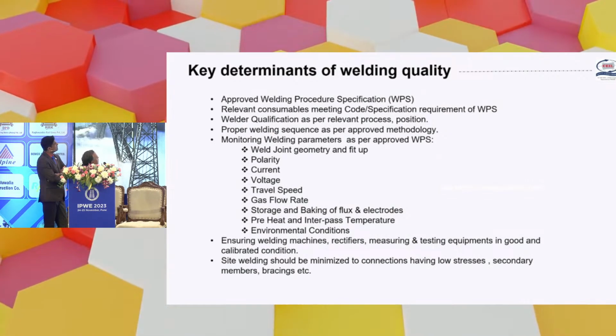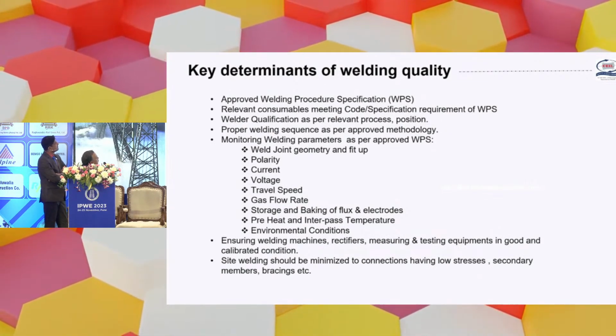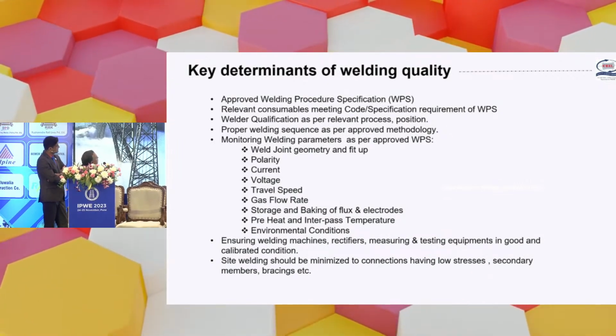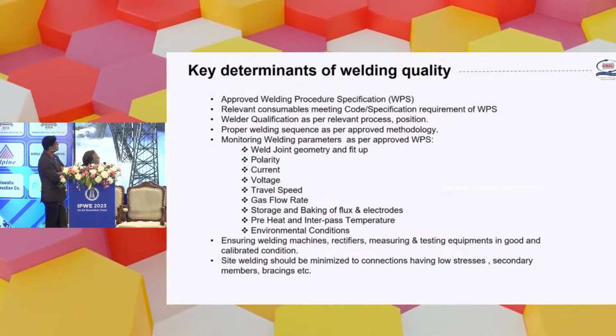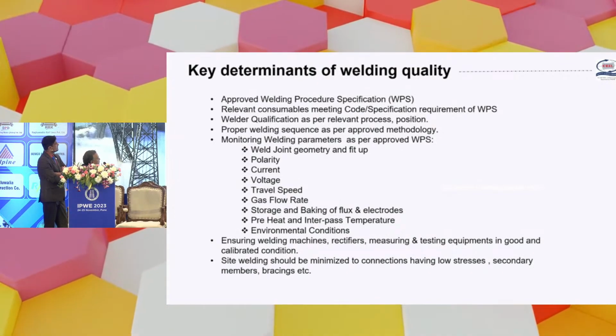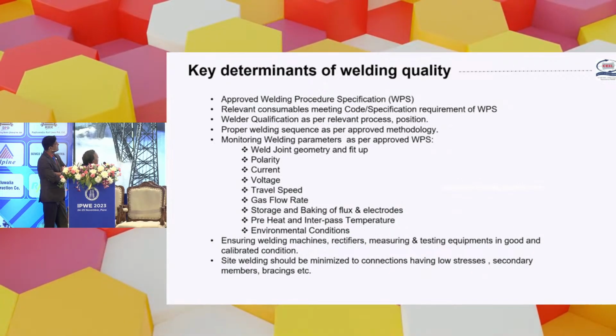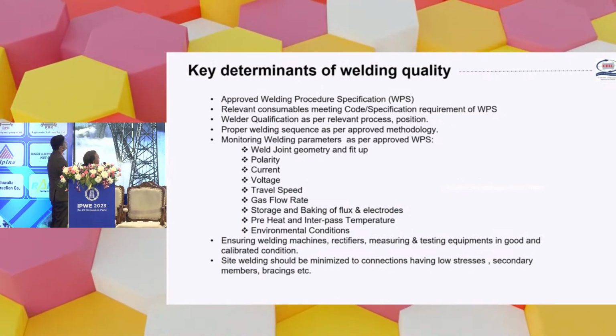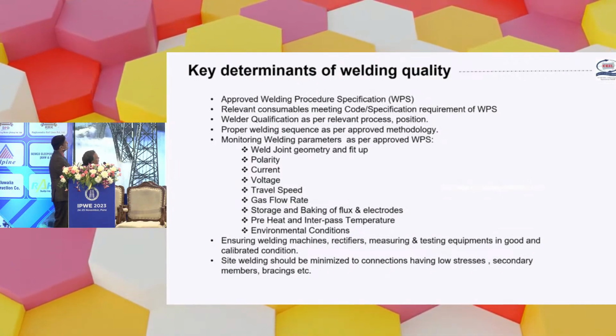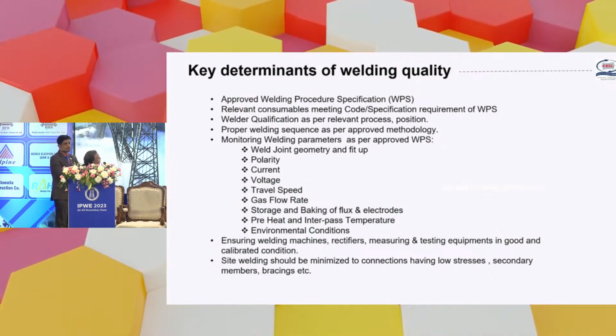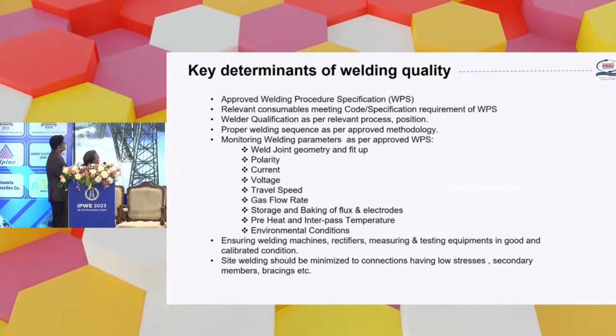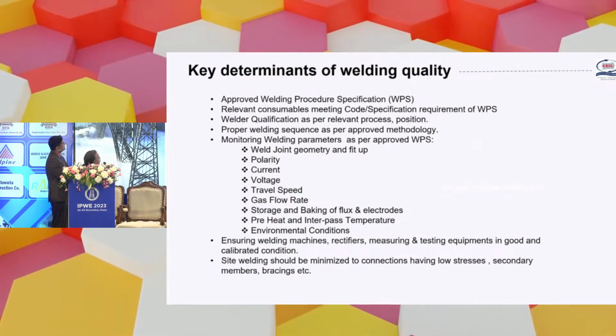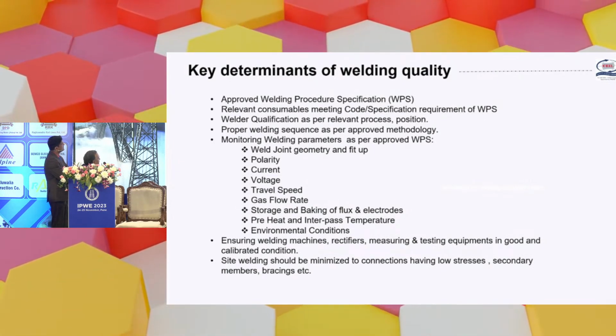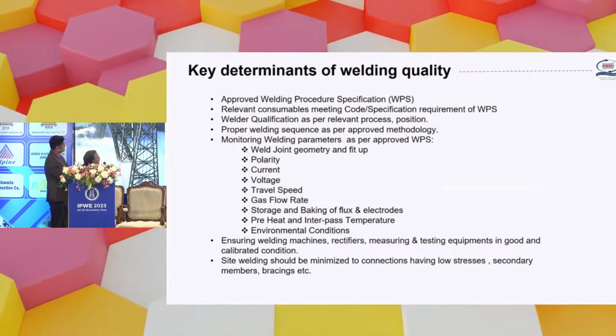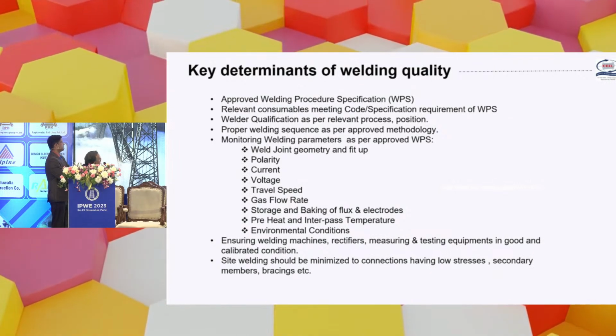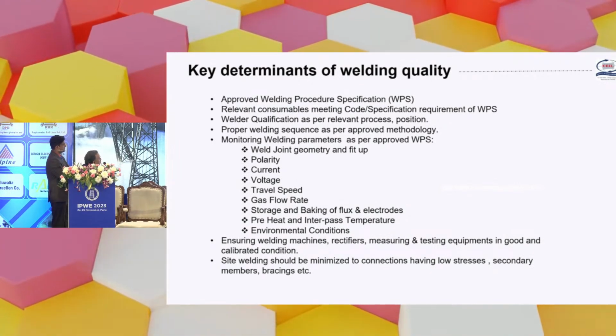So we want to highlight the key determinants of welding quality, during welding and pre-welding. Our engineer always checks these parameters religiously during inspection of welding. We always ensure approved WPSs, relevant consumables, welder qualification as per the relevant process and position, where the position has a vital role. Proper welding sequences, methodology, monitoring welding parameters like weld geometry, polarity, current, voltage, travel speed, and backing, flux and electrodes, preheat and interpass temperature, which is always checked by our engineer to ensure sound quality.